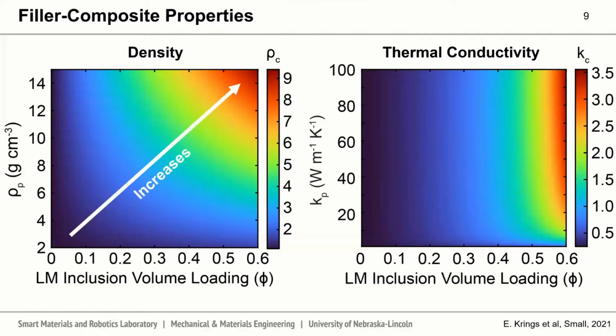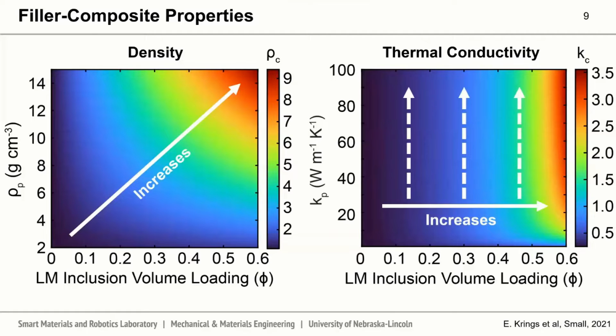If we look at the thermal conductivity of the particle filler, as a function of the volume loading of this particle filler in the composite, where the color map shows the thermal conductivity of the composite, we see a different trend. We really see a major increase in the composite thermal conductivity only as we increase the volume loading of this filler within the elastomer matrix. And we see nearly constant thermal conductivity after some level of thermal conductivity of that particle filler.